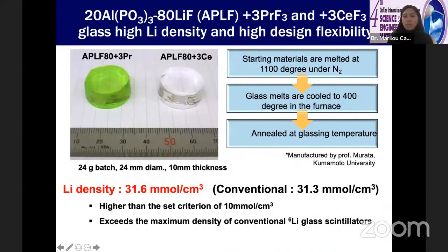So this is the composition of the material that we developed, fluorophosphate lithium glass. It has 80% lithium fluoride content. We use lithium fluoride because lithium fluoride has a high transparency in the UV region, so that will allow the emission from praseodymium and cerium to be transmitted and not absorbed by the matrix.